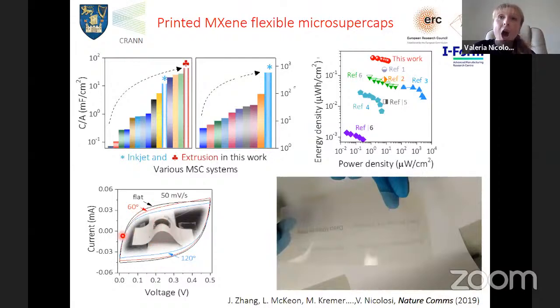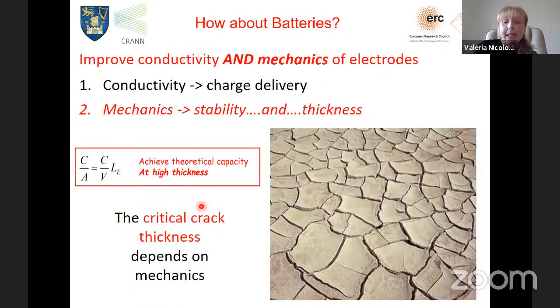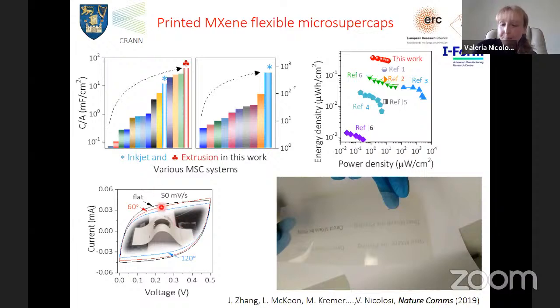This is how, again, the bendability of these devices was really an advantage. You can see how the electrochemical performance is not changing minimally with bending. Here we bend at flat, 60 degrees, 120 degrees. This is a cyclic voltammogram that we collected at 50 millivolts per second, and you can see that there is really no effect on that.